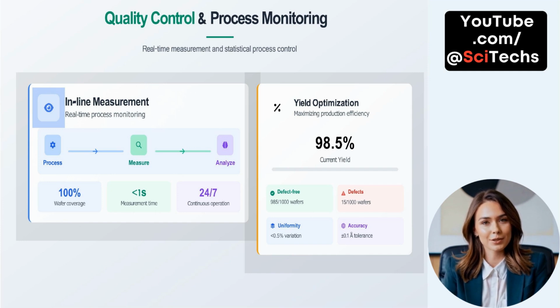On the right, yield optimization is highlighted with a current yield of 98.5%, indicating strong process efficiency. Out of every 1,000 wafers, 985 are defect-free, while only 15 show defects. Key metrics also include uniformity, with less than 0.5% variation and accuracy within plus or minus 0.1 angstroms. Together, these tools significantly improve yield, reduce scrap, and ensure process stability.